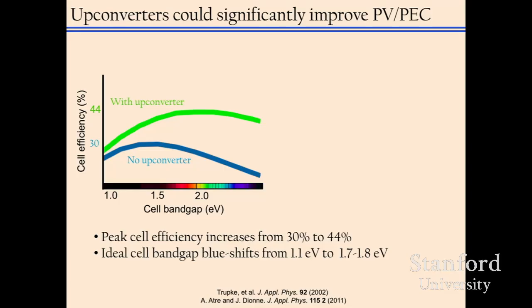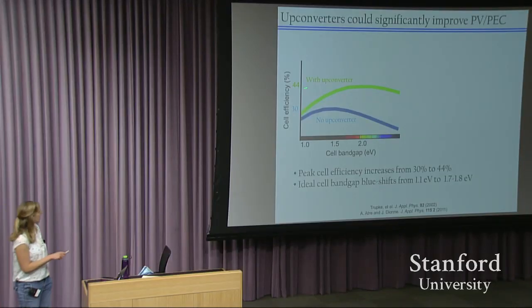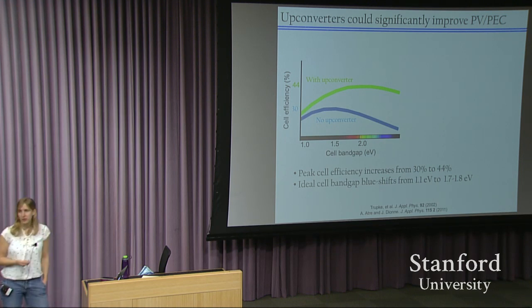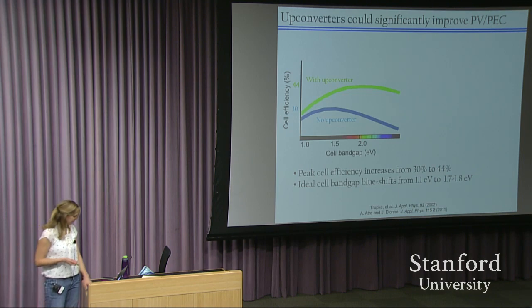So if you look at calculations of how much an upconverter can improve a solar cell, with no upconverter, if you do a thermodynamic calculation, the peak efficiency is about 30% for a single junction cell. And if you add in an upconverter, that peak efficiency jumps up to about 44%. So a pretty significant improvement in cell efficiency.